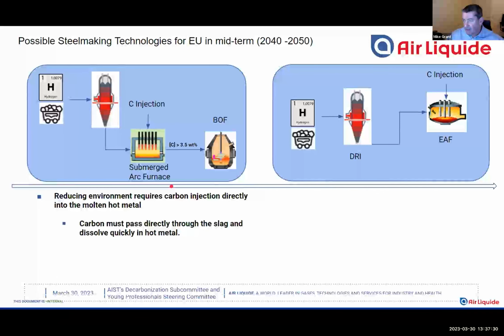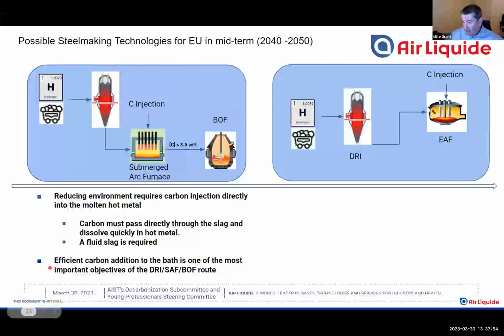So we want the carbon in the hot metal. This means we need a fluid slag. If we have a blast furnace type slag, this shouldn't be a problem. Blast furnace type slags are designed to be rather fluid, so you can get it out of the tap hole. And so we need to be able to inject the carbon through the slag and into the hot metal. Efficient carbon injection is going to be, in my opinion, one of the key technologies. And it sounds simple, but it's going to be one of the key technologies that makes this concept work well.